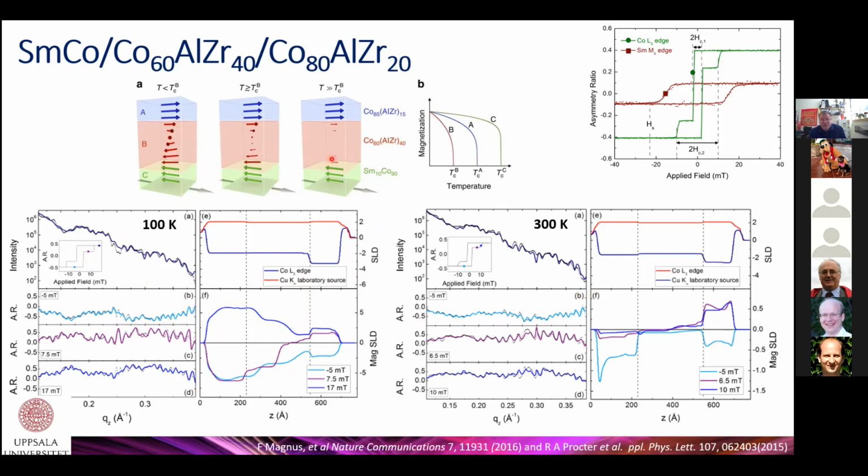And then at high temperatures, where that middle layer should be non-magnetic, we also see that there's some proximity that's being extended through this layer. But it has seriously come down from here. So by setting up sensible models and doing the simultaneous fitting, we've been able to probe the magnetic profile as we went through these tri-layer systems.